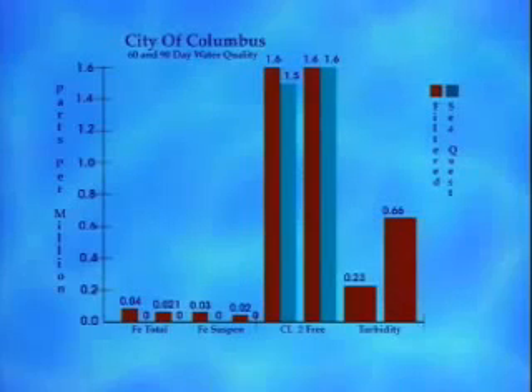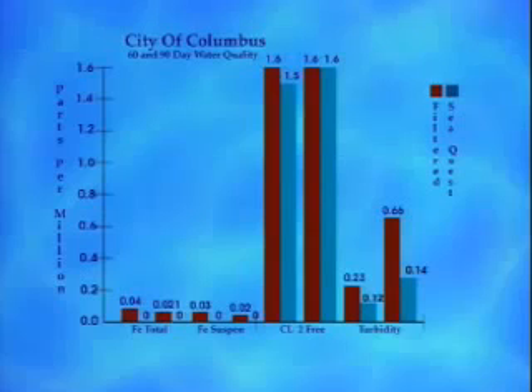So far, all of this data would point to a more corrosive water leaving the plant. However, as we can see, the total iron and suspended iron on the Seaquest side was 0, where the numbers on the lime side were 0.02 to 0.04, showing corrosion occurring in the pipes. The free chlorine remained constant in both sides, as we would expect, and the turbidity dropped from 0.23 and 0.66 to a low 0.12 and 0.14. This drop is partially from the elimination of lime turbidity and partially from reduced iron corrosion.